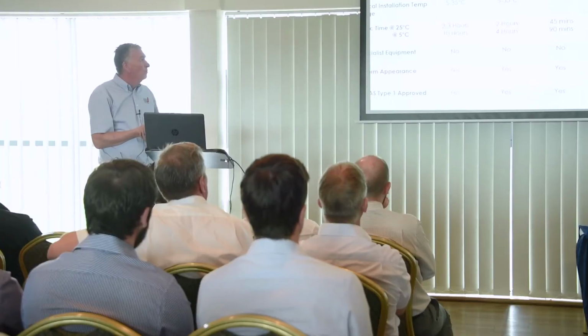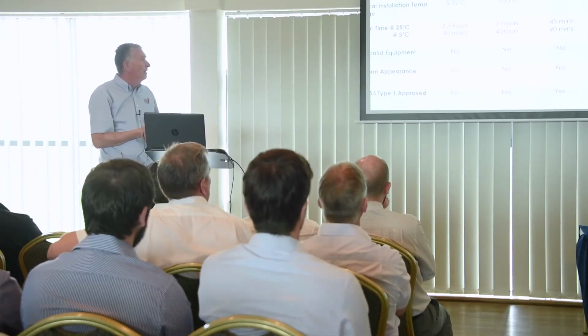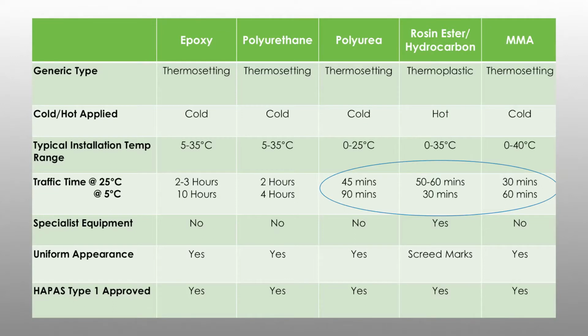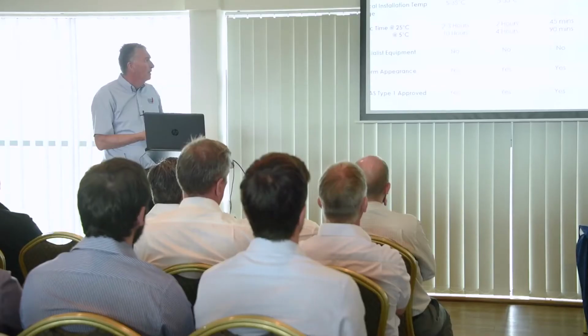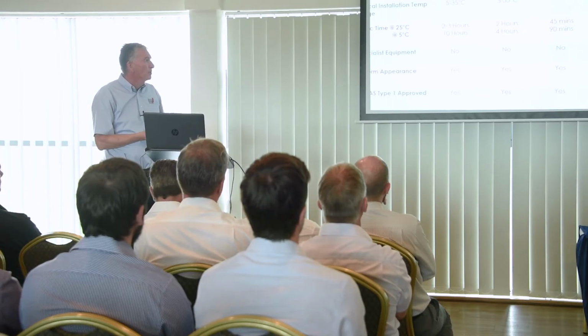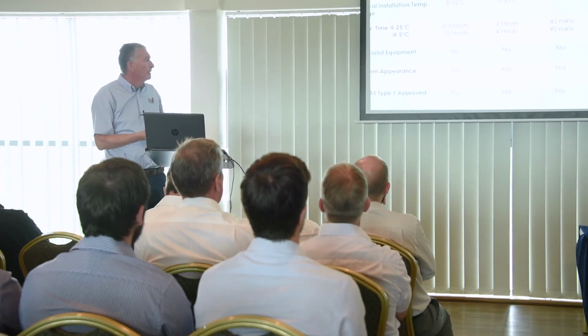Going over to hot applied systems, again, they work by cooling. So when the road itself is hot, it takes about 50 to 60 minutes for it to cool down, but when the road itself is cold, it takes far less, about 30 minutes. And MMA's 25 degrees, about 30 minutes cure time, and 5 degrees, about 60. So different systems have different properties, and you pay your money and takes your choice.